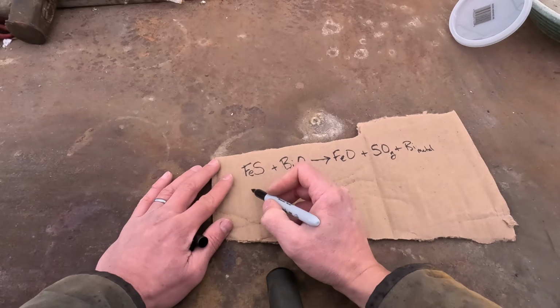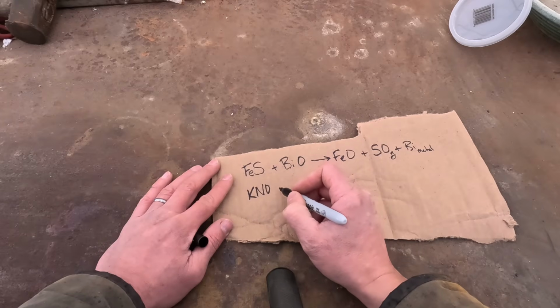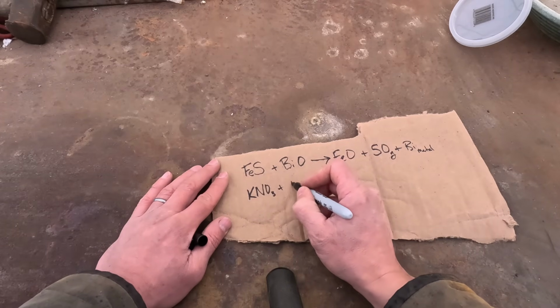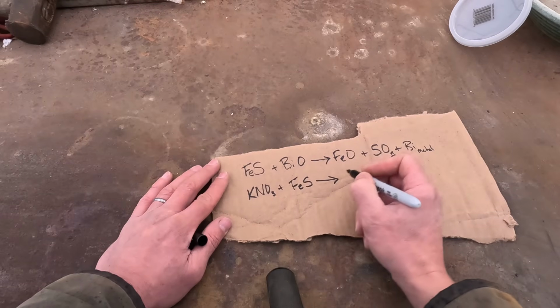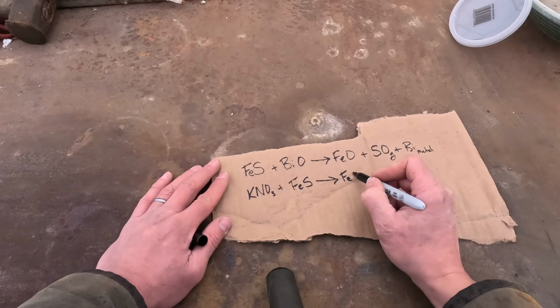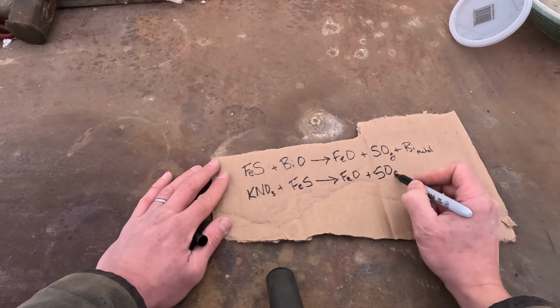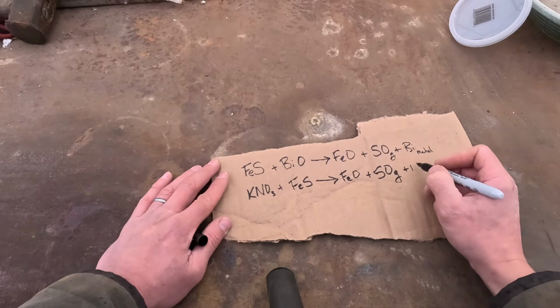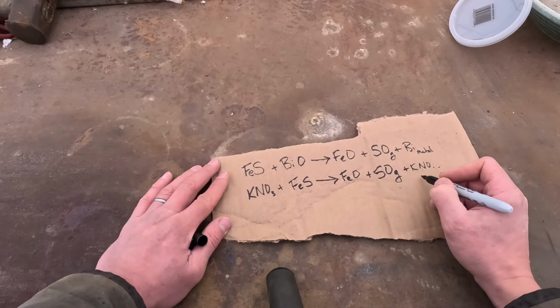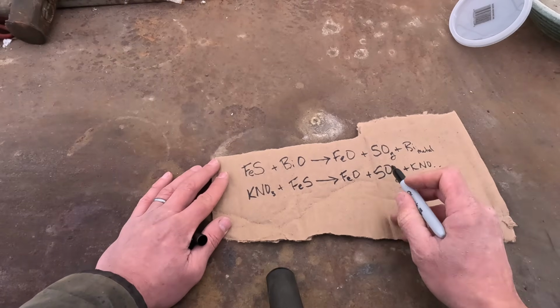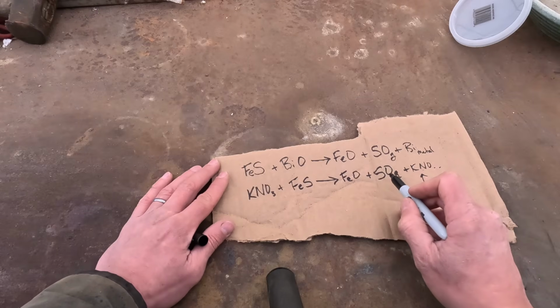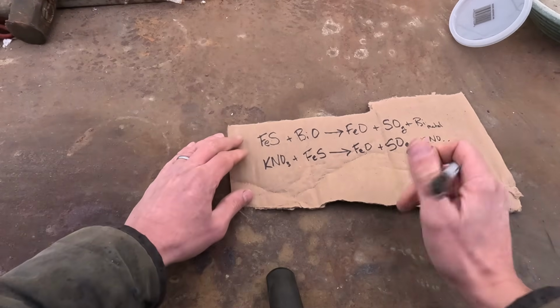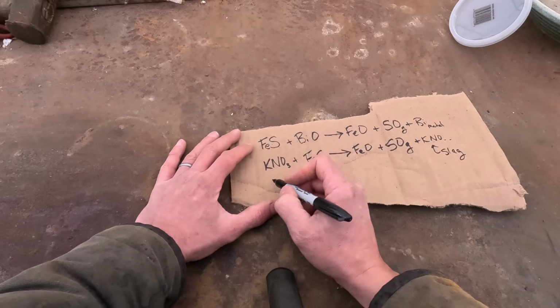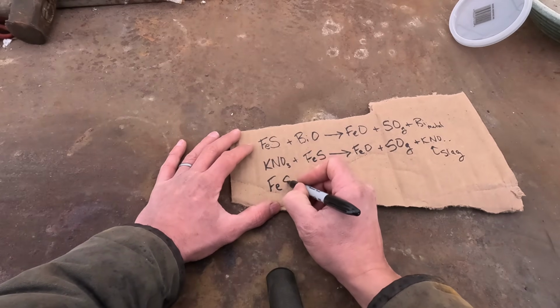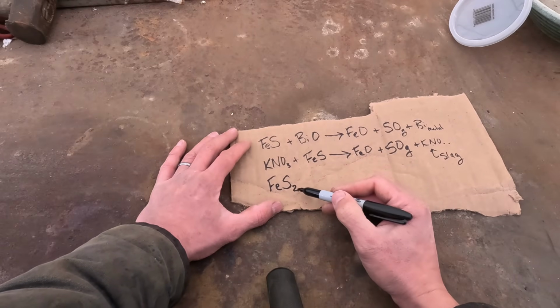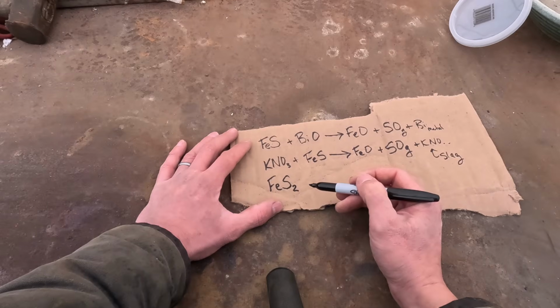If you have a potassium nitrate, KNO3, I think there's a 3 there, but we're not balancing, and it reacts with an iron sulfide, you end up with an iron oxide, a sulfur oxide as a gas, plus potassium NO something, blah, blah, blah. And this goes to the slag. So that's how we're eliminating a lot of our sulfur at the beginning through chemistry. But with the iron, what happens is, and I'm gonna balance this one because it's important to understand, when you have an iron sulfide, this is pyrite, FeS2, so there's 2 sulfur atoms for every iron atom.